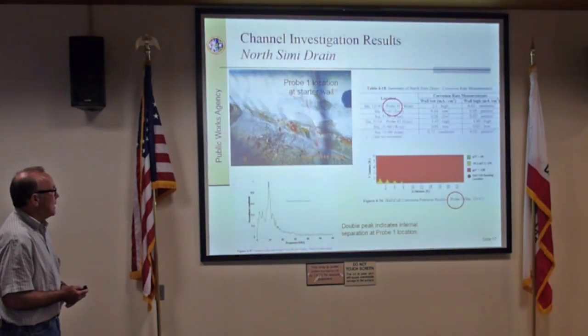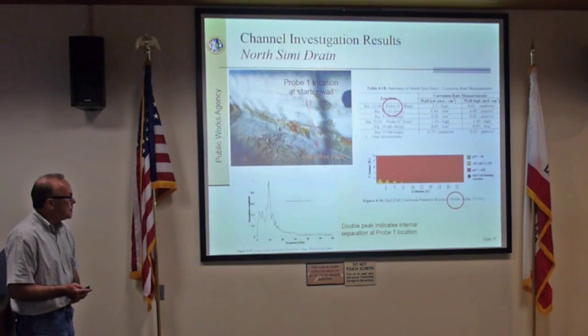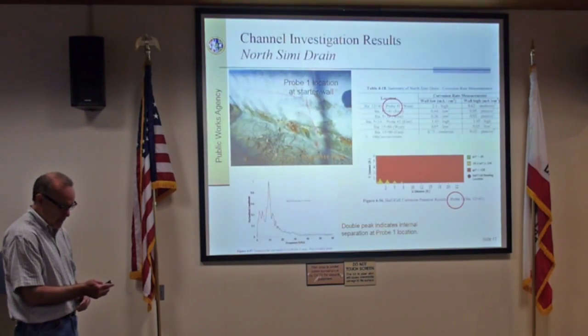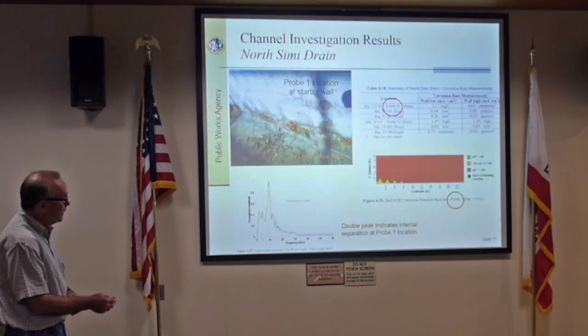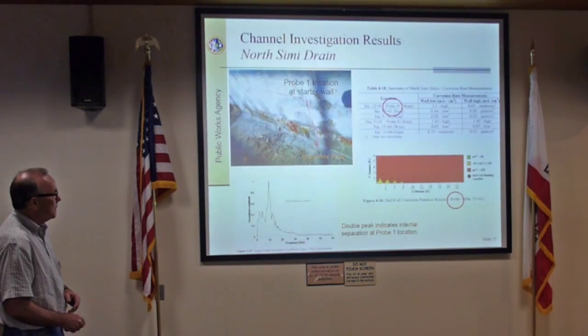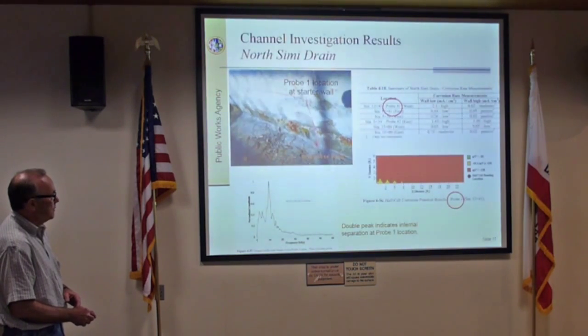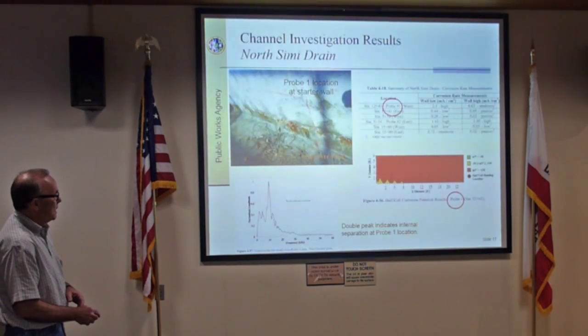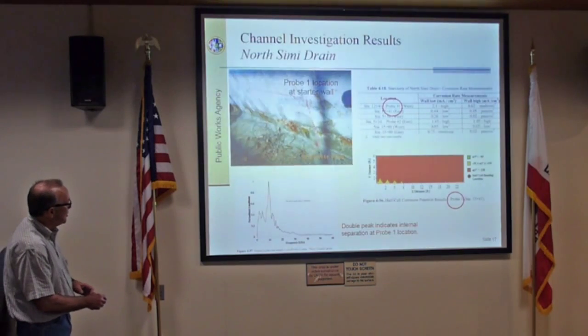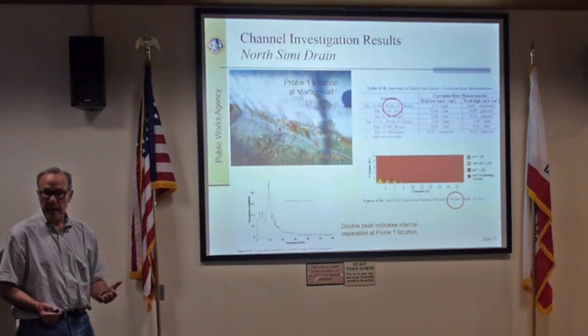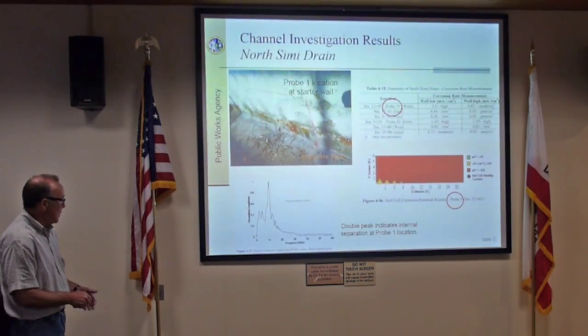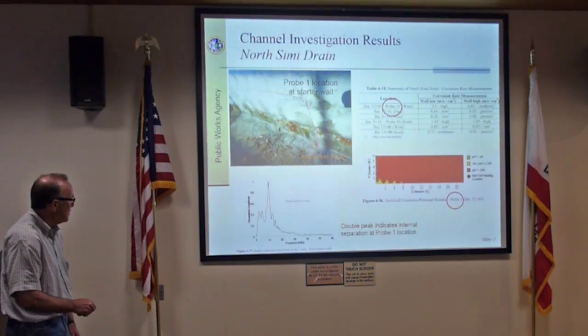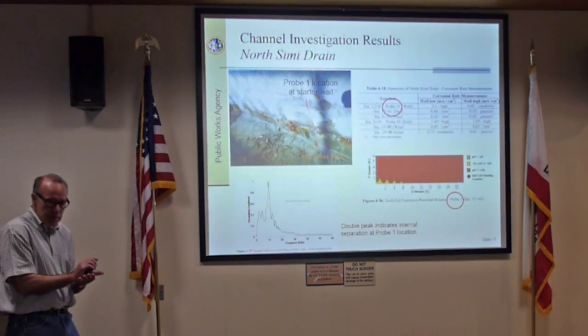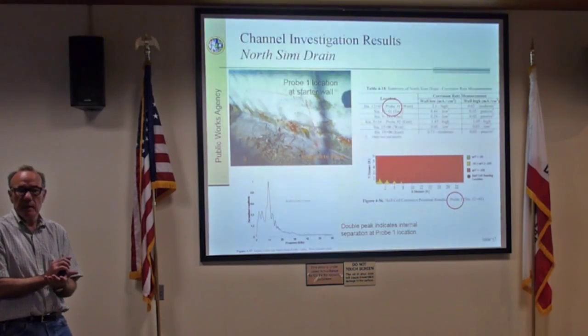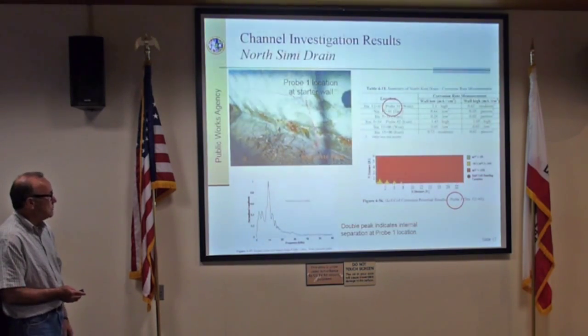North Simi Drain, same sort of data, except in this case you can see the wall is pretty active everywhere in terms of the potential for corrosion. All red. And when we look at the corrosion rates, this 0.44 value, even though it's low, is at the higher end of low, and again, you can see corrosion products coming out of this joint. It's clearly active corrosion, and we detected that with this impact echo test. You can see we don't have that one clean spike. We're getting multiple reflections. That tells us the concrete surface between the wall and the stub wall isn't very good, so it's going to be at higher risk of corrosion.